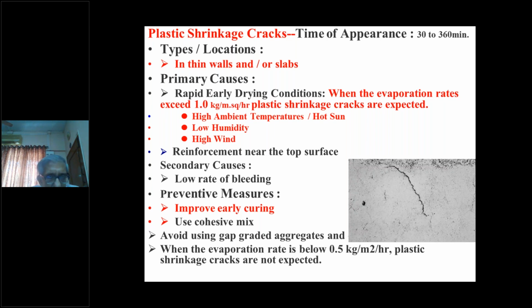The reasons being high ambient temperature, hot sun, low humidity, and high wind. Often people ask the question, why do you need curing during the night? The obvious reason is that winds and low humidity you cannot escape. It may happen at night also. Maybe the hot sun is not present, but loss of water is expected to take place. Reinforcement near the top surface can also cause this cracking.